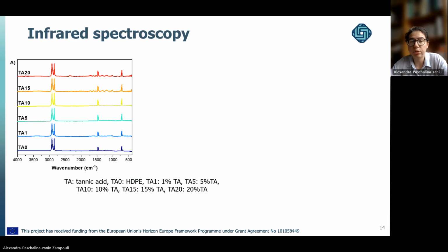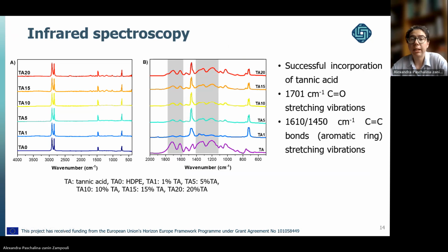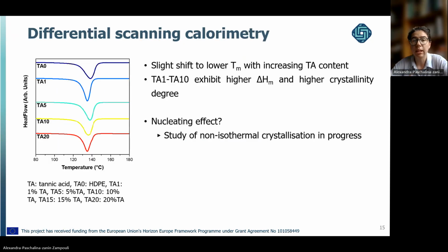Infrared spectroscopy was used to study the materials, and of course we can see the intense absorption bands of polyethylene, but also with a closer look we can see some characteristic absorbances of tannic acid, like the ester bond and the aromatic rings, that confirm that tannic acid has been successfully incorporated in the HDPE matrix.